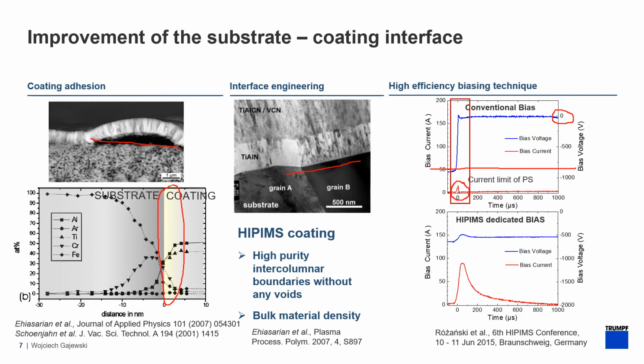On the other hand, you would need a specially designed HIPIMS bias, which can take a high current spike, which will be generated during the HIPIMS pulse, and it will maintain the voltage constant during the operation. It will not only give stability for the power supply operation, but it will also give stability to the quality of the coating.